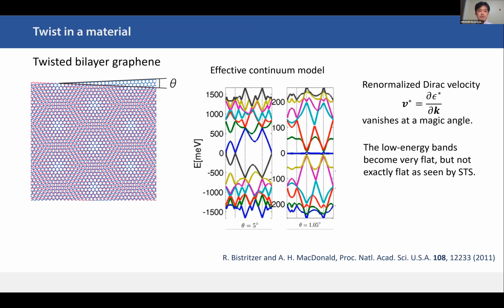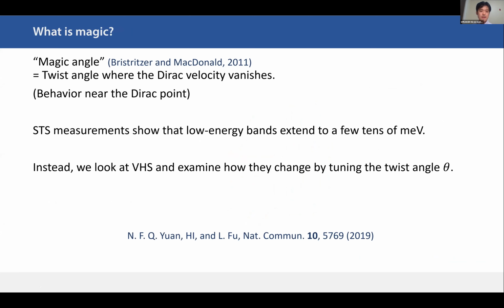This small narrow bandwidth in twisted bilayer graphene was actually reported theoretically by Bistritzer and Allan MacDonald in 2011. They calculated the band spectrum using the continuum model, and at a certain twist angle, they found very narrow bands near zero energy at the Fermi level. But as we have seen from the spectroscopy measurement, this band is very flat, but not exactly flat. Bistritzer and MacDonald termed this special angle the magic angle, and they defined the magic angle as the twist angle where the Dirac velocity vanishes. But as we have seen, the bandwidth is not exactly flat, even at this so-called magic angle.